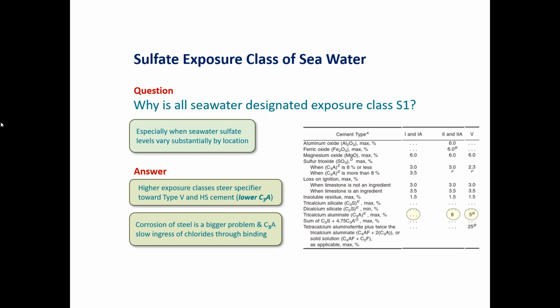And so the tendency by the old school ways of handling sulfate attack is, as you can see over here, this is a little blip from ASTM C150, and the difference between type 1, type 2, and type 5 cement. The main difference is going to be the C3A content. And as we said earlier, you have to have the hydration reaction component of C3A in order to have sulfate attack. So type 1 does not have a limit, and you can see ranges that go over 8%, and I've seen them in the 11, 12, even possibly 13% range. So you have a lot of this stuff.